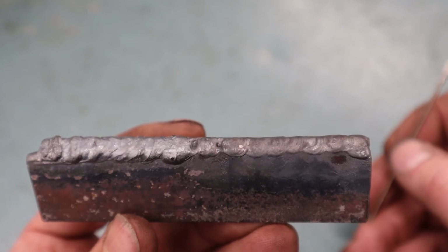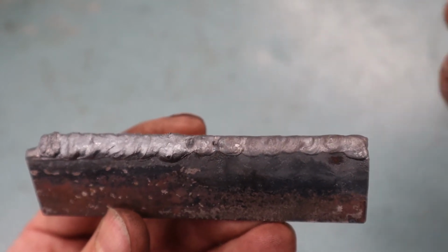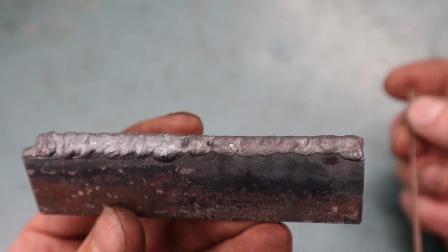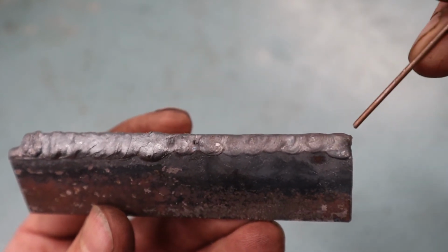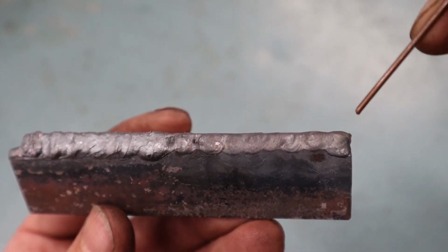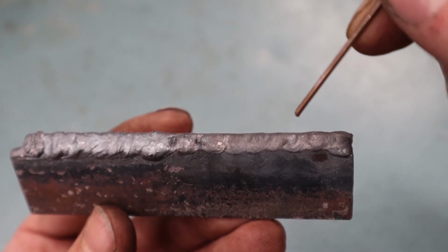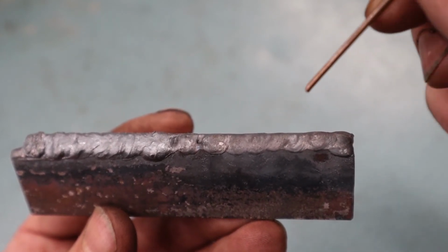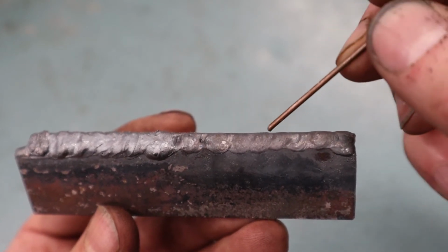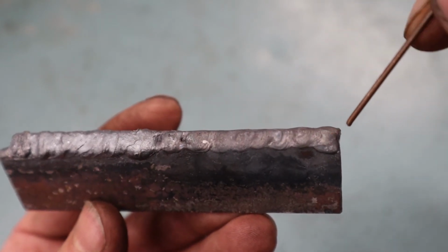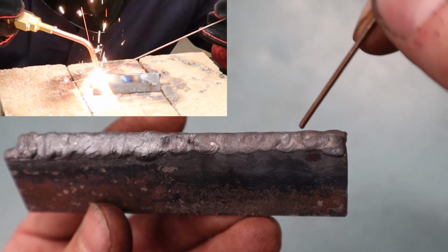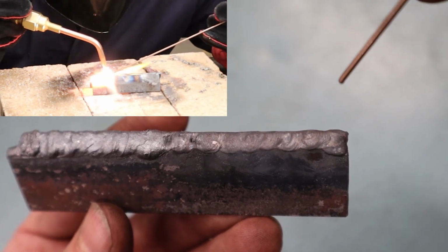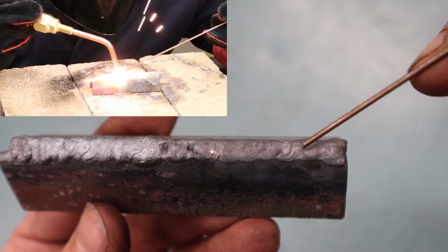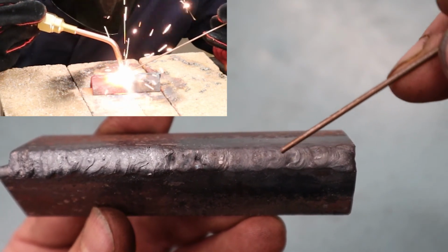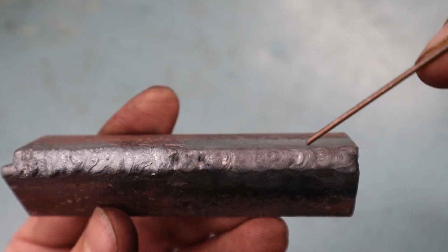So here's another sample that has two other common conditions found when gas welding. On this side of the sample, this is irregular movements with the torch. So rather than making a puddle, filling it up, and slowly moving over in the direction of travel, kind of robotic-like, rhythmic-like, putting in your filler rod, this person has made a puddle, put in some filler rod, and then jumped over about four or five millimeters and made another puddle, filled it up, jump again. And so you can literally see that in the movement. There's one puddle, two, three, four, instead of nice little C's that are evenly spaced out.